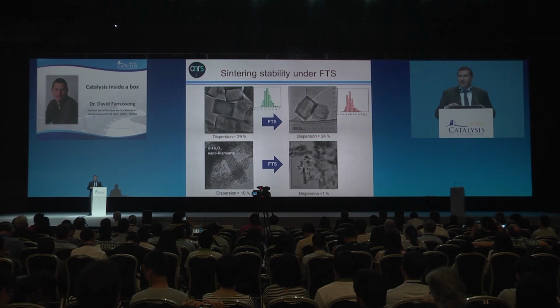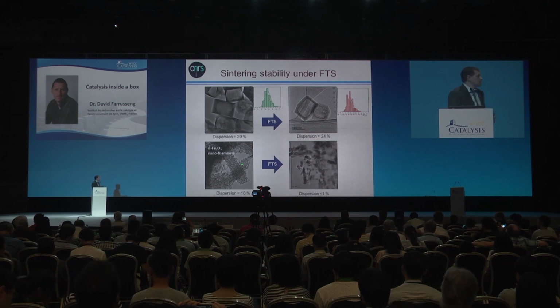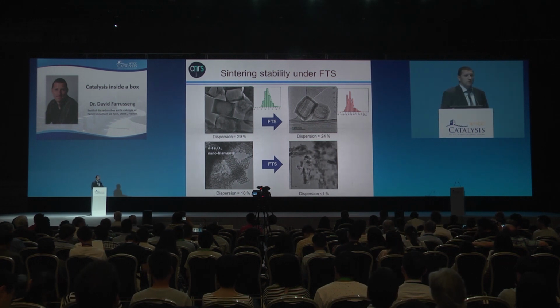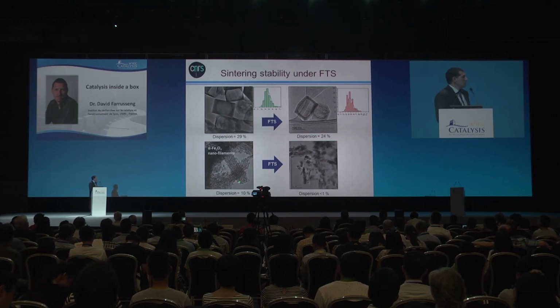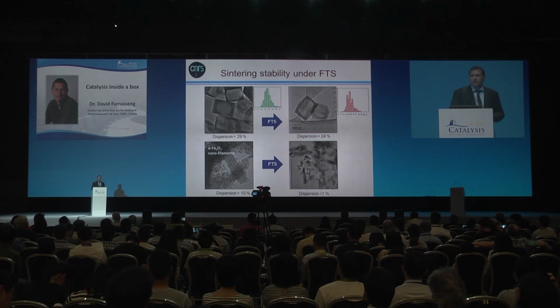If you apply the same treatment to iron nanoparticles without any support or just a silicate, then even at such high dispersions, they will completely sinter in the Fischer-Tropsch conditions and lead to very poor activity.